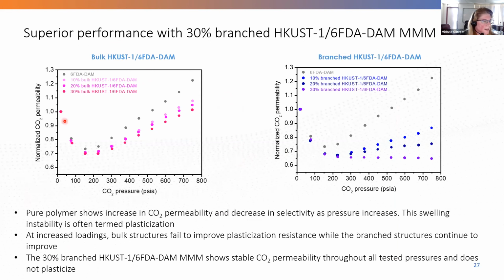A couple of things I'll first point out is that the individual polymers themselves, when you see an increase in the permeability as a function of gas pressure, particularly for CO2 permeability, it means that these membranes are plasticizing. So the environment that they're in is actually causing them to chemically get modified. And as you increase the loading of the bulk structures, you see a little bit of improvement, but you're still seeing a lot of plasticization of these materials.